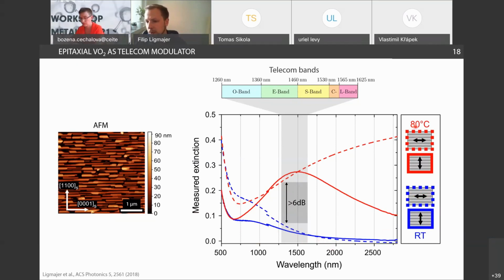But as you push your VO2 into its metallic state by heating it up, you can get a very nice localized plasmonic resonance in the transverse direction, so when your polarization is across the beams, and also you get some sort of longitudinal plasmonic resonance at very large wavelengths in the mid IR. It was fortunate for us that the region of the highest change, the highest tunable window, was across the quite important telecom bands, where a lot of optical communication is done. And the extinction ratio, that means the metric of how the extinction changes, was also quite significant.